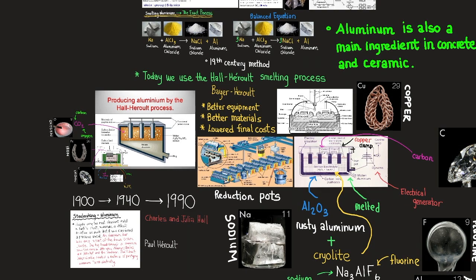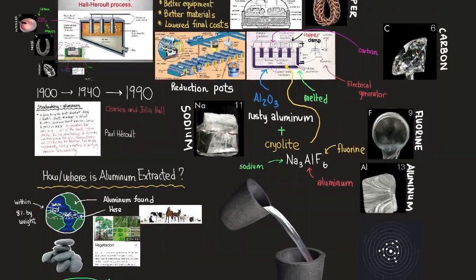About 450 grams or 1 pound of carbon are consumed for every kilogram or 2.2 pounds of aluminum produced. About 2 kilograms of alumina are consumed for each kilogram of aluminum produced. So the smelting process is continuous. Additional alumina is added to the bath periodically to replace that consumed by reduction. Heat generated by the electric current maintains the bath in a molten condition till the fresh alumina dissolves. Periodically, molten aluminum is siphoned off.